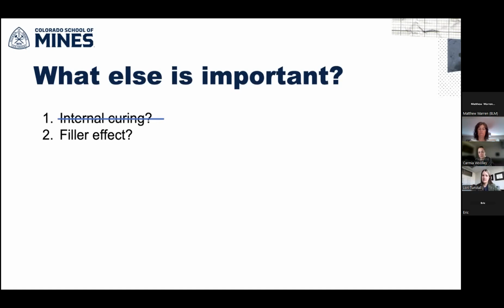Another effect considered is called a filler effect, and this is the idea that when you incorporate small particles into a composite, you get a twofold effect. One, you get a lot of surface area for hydration products to nucleate on. In other words, you get surfaces that promote growth, and that is typically associated with the surface area of the material. Another part of this filler effect is efficient shearing. It breaks up the dry cement particles more effectively, increasing the total hydration. Again, we would expect both of these effects from the filler effect to be associated with high surface area and particle size and some other effects that we've looked at. None of them correlate with strength gains. So we've also ruled that out.